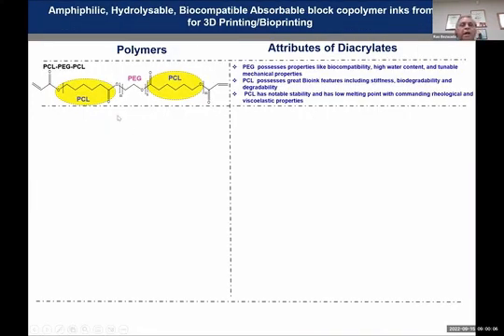These are amphiphilic polymers having hydrophilic and hydrophobic blocks. PEG provides the hydrophilicity and PCL provides the hydrophobicity. It also provides strength and elasticity to the PEG. In this molecule, you can change the PEG molecular weight from 1,000 to 20,000, and you can have PCL blocks anywhere from 10% to 30% in a water-soluble acrylate polymer.